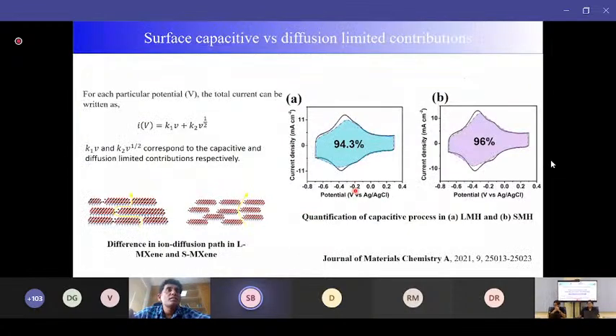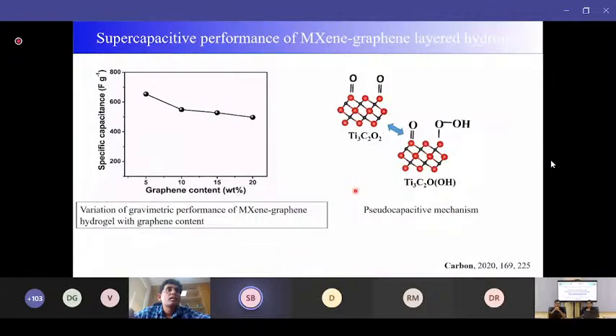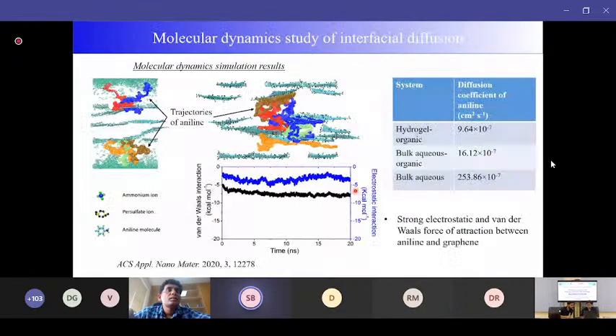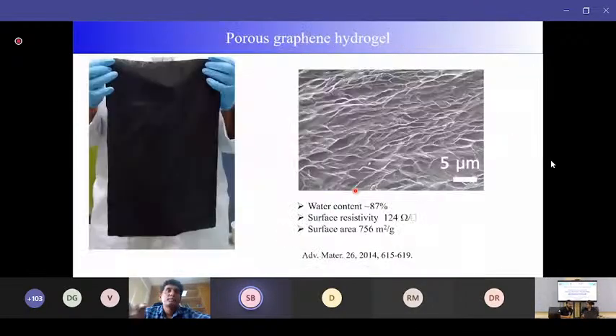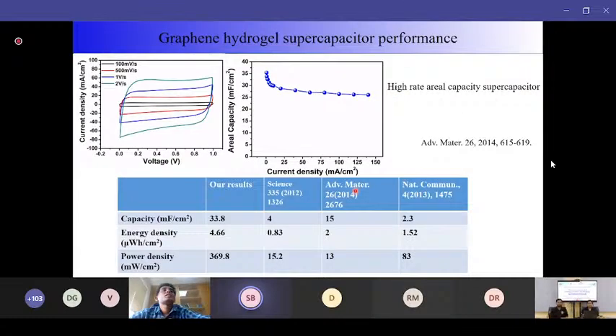Let me go to one of the CV curves. So you see that here I have used a 1 volt window, from 0 to 1 volt, because I have used an aqueous electrolyte. In an aqueous electrolyte, water generally dissociates. The dissociation energy, if you convert it to voltage, is 1.23 volt. So if you use 1.23 volt, water will dissociate. You don't want the dissociation of the electrolyte, so you have to be within the limit of its dissociation potential. In this case, I have used up to 1 volt, although theoretically I can go up to 1.23 volt.